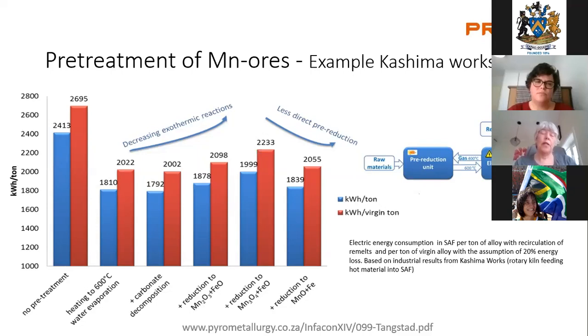If they calculated what could be gained in the different steps of pretreatment, heating, carbonate decomposition, and some of the reduction, some steps reduce the consumption, and some can give an increased consumption because you lose some of the exothermic reactions in the furnace and move them over to the pre-reduction instead. But at the end, you will have reduced the consumption of electrical energy by around 400 to 600 kilowatt hours per ton, depending on how much you pre-reduce. This is a considerable amount, and it has been done for several years at Kashima Works. So, next slide.